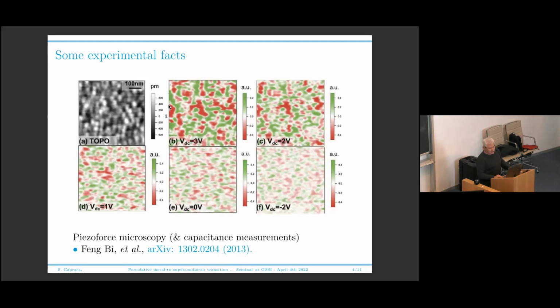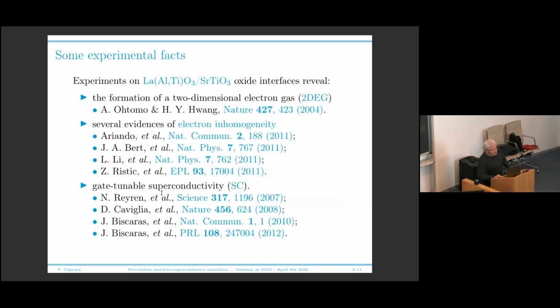I will give just some piezo force microscopy experiments where you see that you have domains. Just to have an idea, this is 100 nanometers. So you clearly see the formation of domains in this system. Maybe these are self-organized, we don't know. Maybe they are introduced by some defects at the interfaces. We don't really know, but what we see is that there are these domains. And what is even more interesting is that this two-dimensional electron gas can become superconducting.